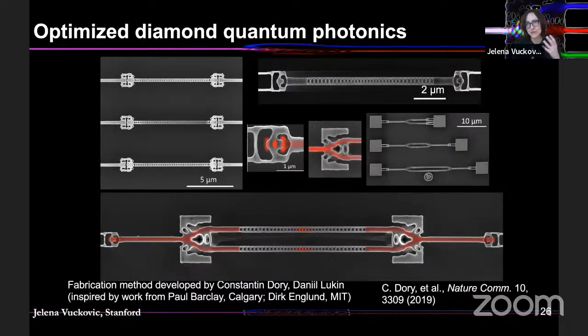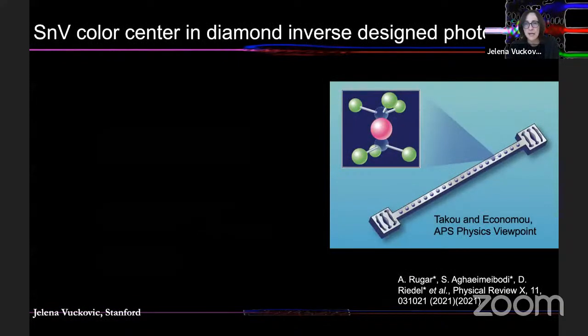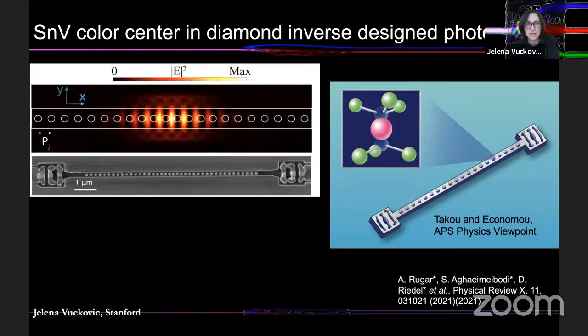But of course, diamond is not an easy material to process, and fabrication is not really trivial, but we're able to make very high quality structures in the process. And I'll show you some of the exciting experiments later on. And this is also compatible with the inverse design that I was talking about. So here you see some non-intuitive elements that are splitting light and combining emission from two different resonators. And we can do all of this fabrication without affecting properties of the color center, like tin vacancy in diamond.